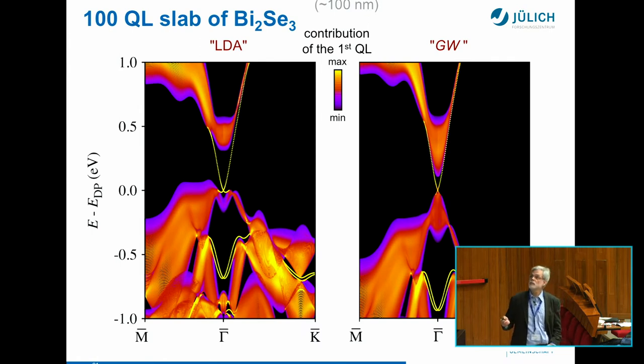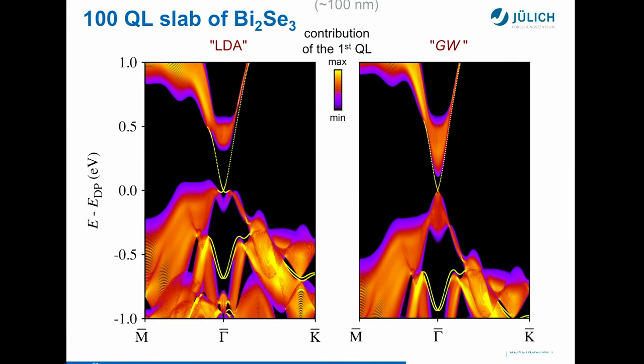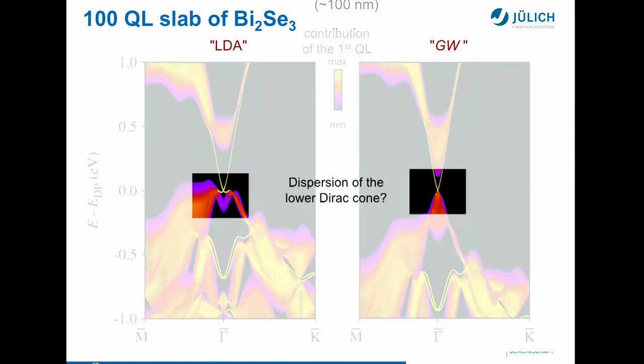And here you see a calculation for bismuth selenide. You see an LDA calculation with this very famous Dirac state, Dirac point. And here you see a GW calculation with the Dirac point. First of all, you see in LDA, bismuth selenide is an indirect band gap semiconductor. And you see in GW, it's a direct band gap semiconductor. The Dirac point looks totally different. How does it compare to experiment? So we look at only this